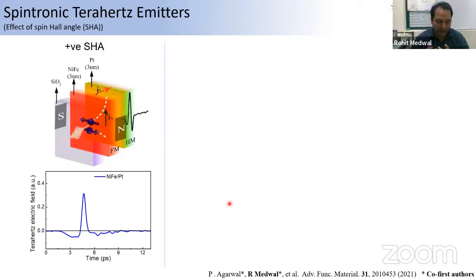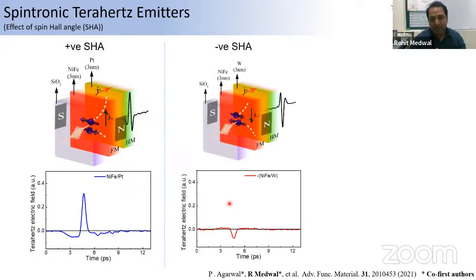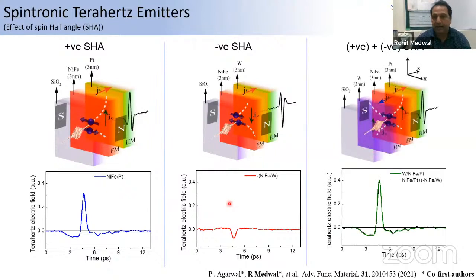Permalloy is NiFe. I always call NiFe a permalloy. So NiFe, or the permalloy, interfacing with tungsten, which has a negative spin Hall angle, and permalloy interfacing with platinum, positive and negative spin Hall angle. So what I can clearly show you here is that for positive spin Hall angle, the terahertz electric field is positive, and for the negative spin Hall angle, the terahertz electric field is negative.